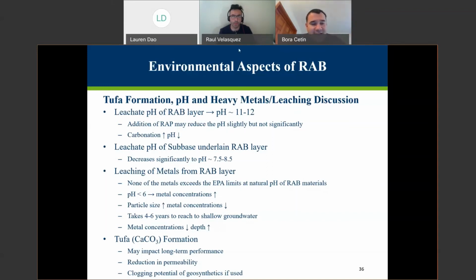And our numerical models show that it takes 4 to 6 years for these elements, contaminants, I mean, not contaminants, but these metals, to leach even to shallow groundwater. And when it reaches there, it's already dispersed. If it leached 10 milligram per liter, I'm just making up a number, let's say iron leached 10 milligram per liter, by the time it reached the groundwater, it turned out to be 0.001 milligram per liter. So it dissipates over time.